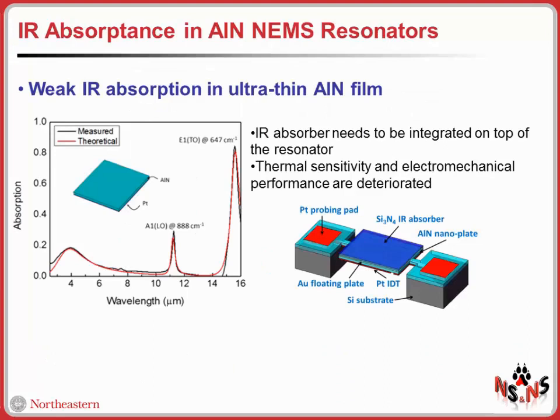But one very important challenge that we have with these piezoelectric resonant thermal detectors in general is that the infrared absorption in such an ultra-thin aluminum nitride piezoelectric plate is quite weak. Here you see the infrared absorption spectrum of a 500 nanometer thick aluminum nitride film measured in the 2 to 16 micron range. And you can see that beyond these two vibrational peaks of the aluminum nitride, the infrared absorption is quite low.